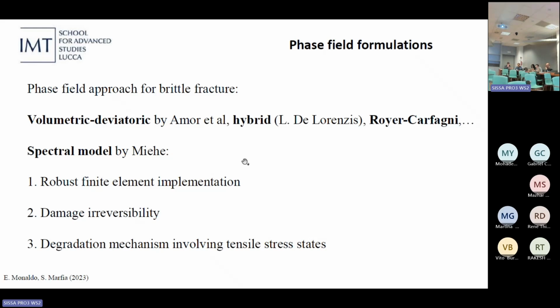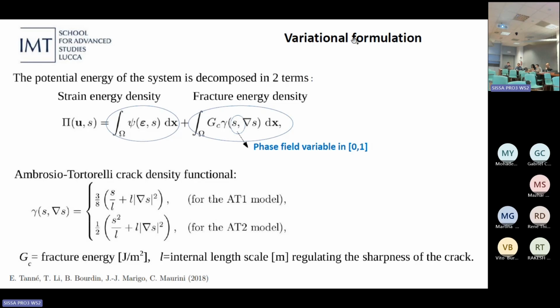kind, basically. So here what we have, the variational formulation of the problem in the regularized framework. Basically, the total potential energy of the system is decomposed in two terms. We have the strain energy density of the material, which is a function of the strain, and this variable s, which is the phase field variable, which is a damage variable taking values in the interval 0, 1. 0 means intact material, and 1 means fully damaged material.